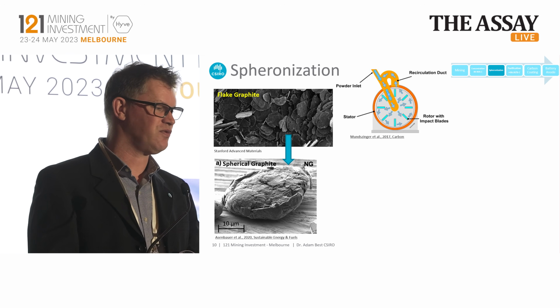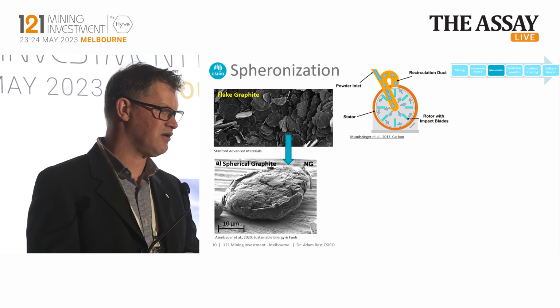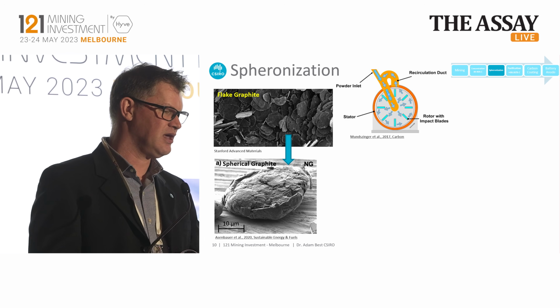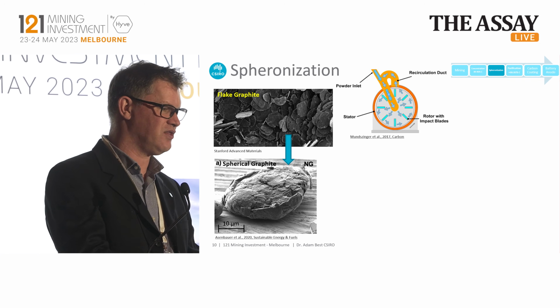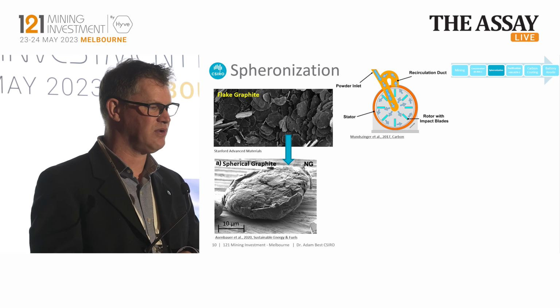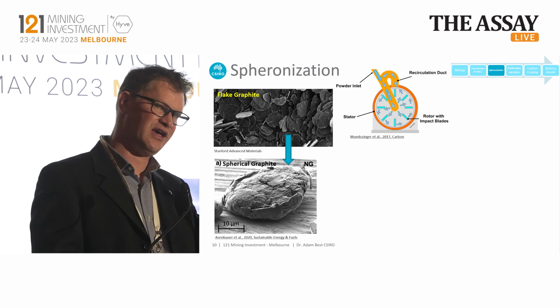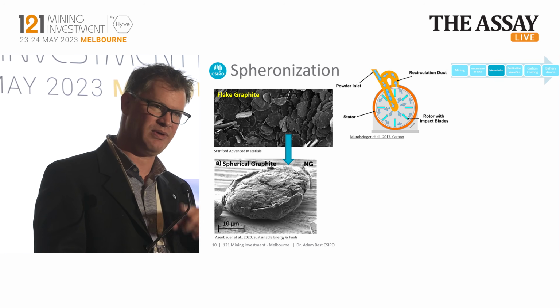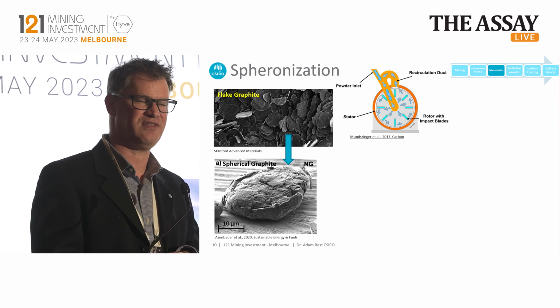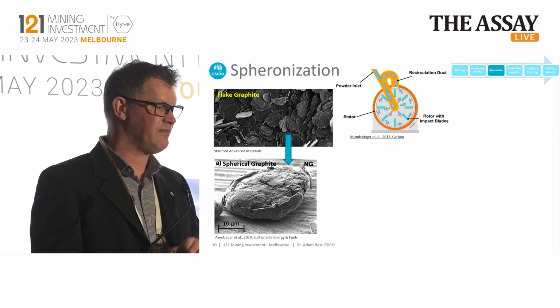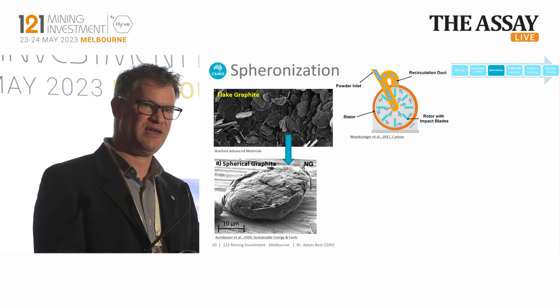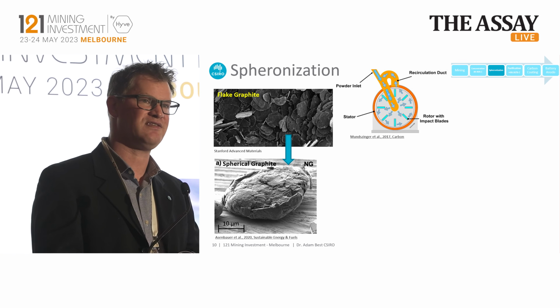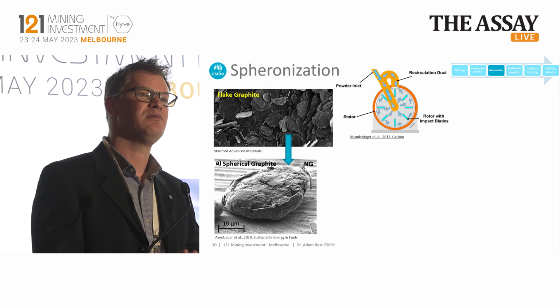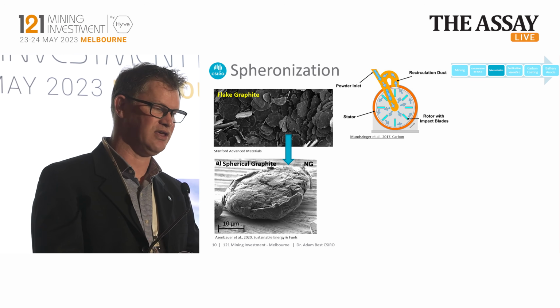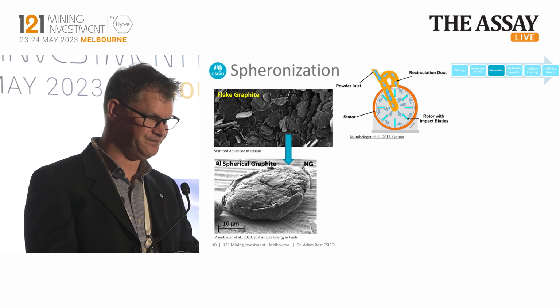So there are a number of different ways to do this. We at CSIRO, we use a NARA hybridizer, and what this does is we have a feed on the top of that instrument there where we can feed the powder in, and through a rotationary process this balls up the little flakes into the spheroids that you see on the left hand side. The NARA hybridizer is not a cheap piece of equipment, but it's far more efficient than, say, a spheronizing train that you would buy from China, which is cheap and cheerful, but does not have the high yields that you would potentially like to have.